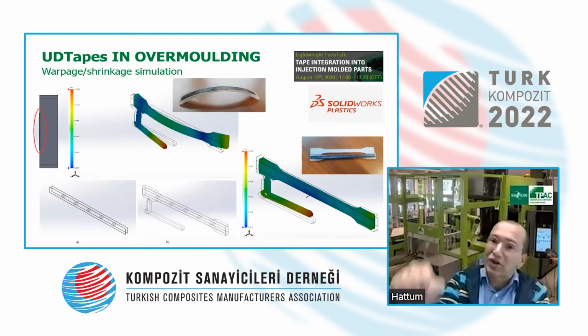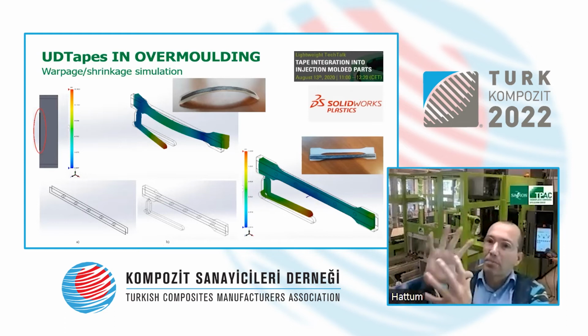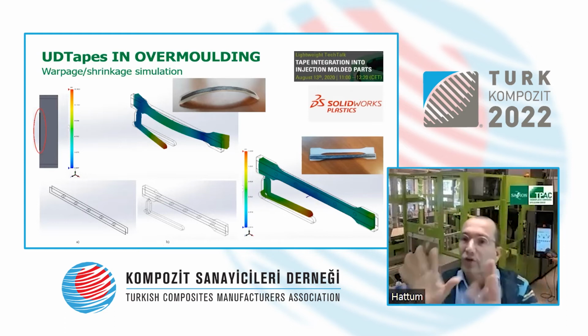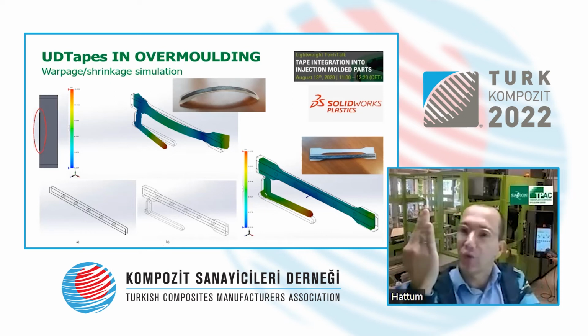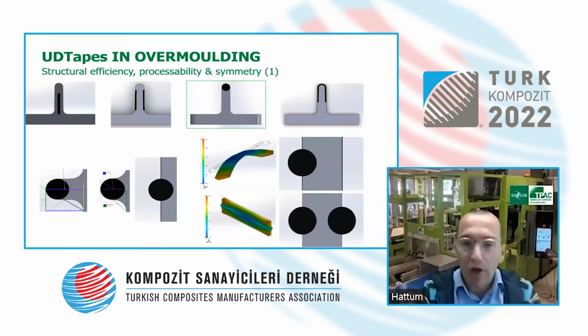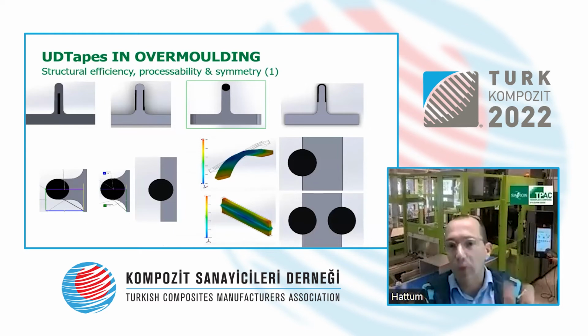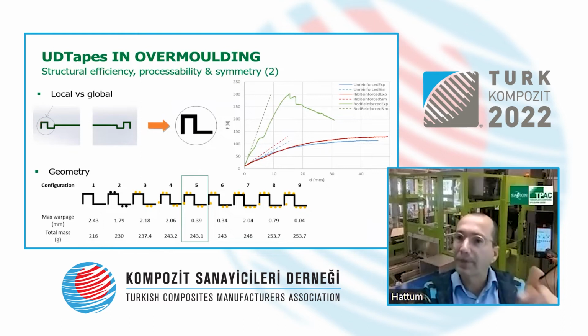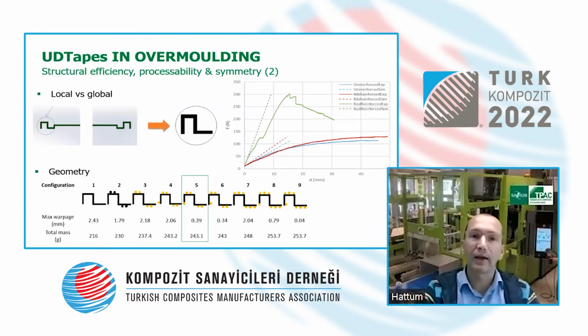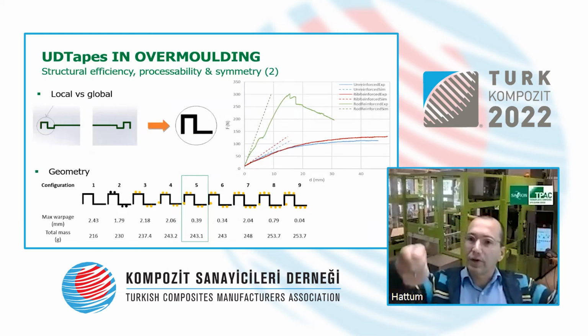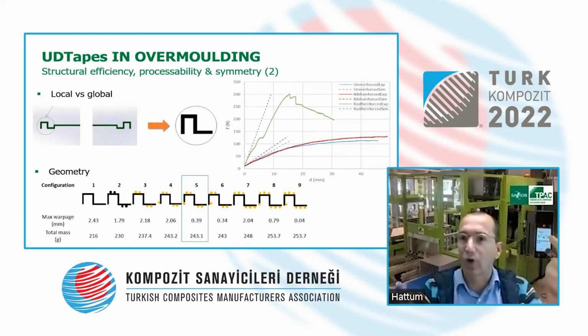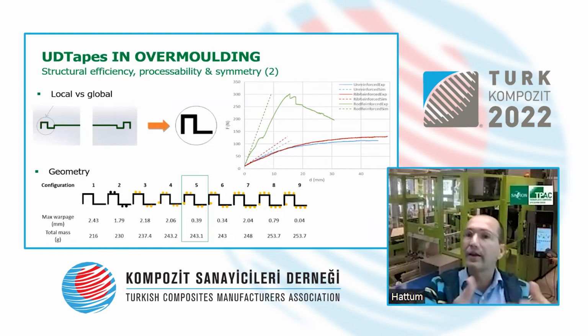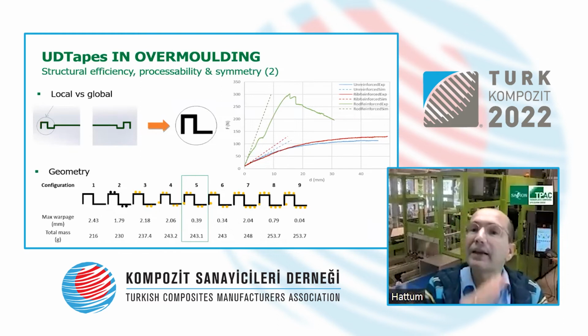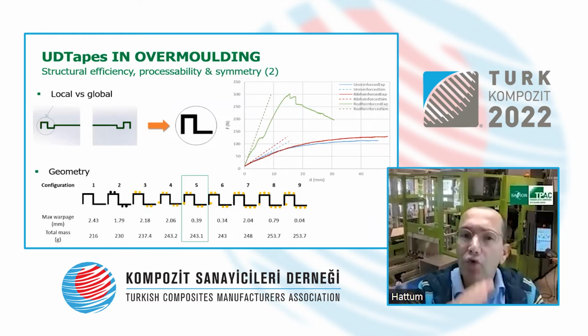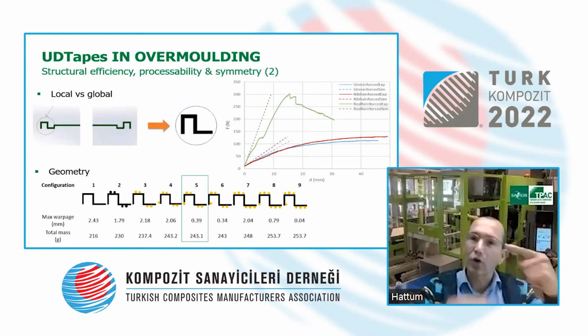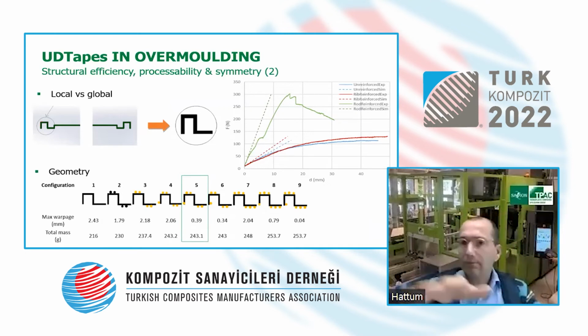Remember the midsection of the car. If you have these complex creations with local reinforcement, in the end, your whole part might be doing this. You don't want it. A lot of considerations where to place the fiber, in which quantities. We do a lot of simulation and optimization schemes. In this specific case, it was a foldable crate. So if you have crates for transporting apples and oranges, etc., they're typically injection molded, polypropylene, polyethylene. But I believe there is 2 million of those crates just from one supplier continuously rotating in the business.